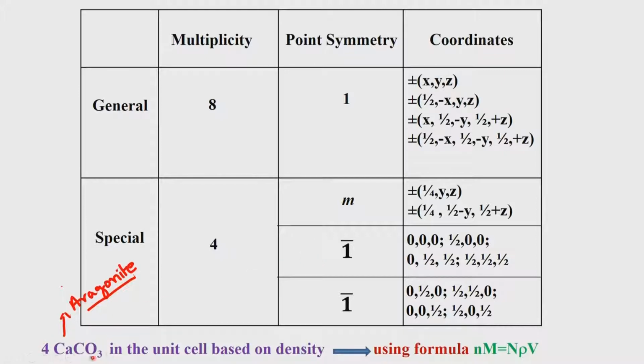On the other hand, there are 4 times 3, there are 12 oxygen atoms. So, these oxygen atoms have a very clear liberty of how they could arrange in generating the calcium coordination, because these 12 can be, say 8 of them can be sitting in general position and 4 can be in any of these 3 special positions. That is one option. The other option is 3 types of oxygen sit in each of these 1 bar and M positions. That will also total up to 12.